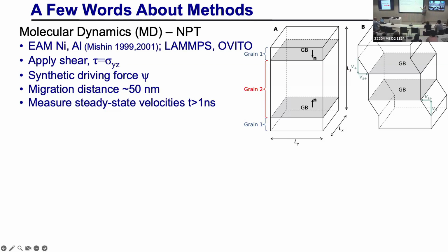Now, as I mentioned a moment ago, I can also apply a shear. If I shear the crystal like this, it turns out that the grain boundary that was here may migrate upward at the same time as the crystal shears over. This is a general phenomenon we call shear coupled migration. It applies to almost all types of interface motion: there's a coupling between the motion this way and the shear that way. If I make the boundary move like this, the crystal will spontaneously shear, and if I shear it, it'll make the grain boundary move. I can do it either way.